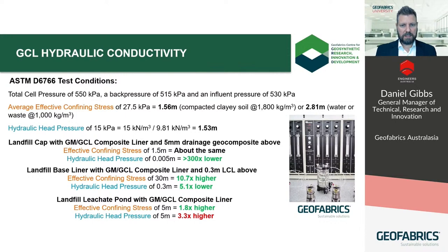The pressures were selected to ensure the specimen could be confined and back pressure saturated using a hydraulic gradient that would produce a flow so that measurements could be made in a reasonable time period for QC and commercial labs. These specific pressures were reached by consensus at the time and only meant for comparing one GCL specimen to another based on the standard.